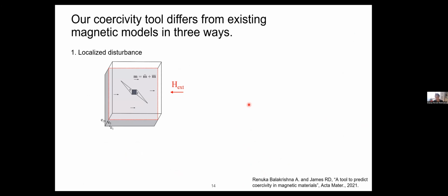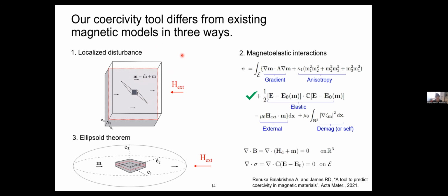Okay, so the key features of our work is we model a three-dimensional domain, which is about 250 nanometers in diameter, and you have a non-magnetic inclusion, which is at the center of this three-dimensional object. So the surfaces don't see the defect, but it's just a small pore-like defect that's placed at the geometric center. And so you form this kind of a needle domain that forms in one of the surfaces inside of your material, and you apply an external field. And this is how we are splitting the magnetization. So we're actually modeling a large ellipsoid where this domain is buried at the center. So when we predict the coercive force of a specific combination of constants, this is for a bulk alloy.